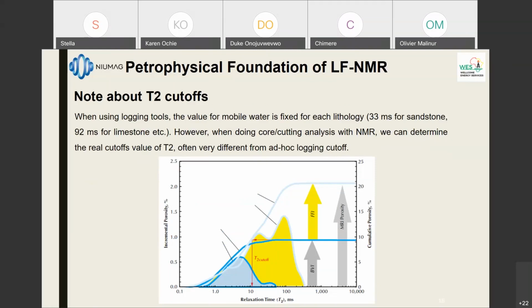So why is it important to do this? It's important because when you use logging tools, they have fixed cutoffs for the T2. They say it's 33 milliseconds for sandstone, 92 milliseconds for limestone, 3 milliseconds for clay, etc. But when you do core cutting analysis with NMR, you will discover that this cutoff is completely off. It's not corresponding at all. And very often, you end up with a change in your recovery factor, because the bound fluids and the free fluids will give you later on, ultimately, your recovery factor. So it's very important to determine the T2 cutoff.